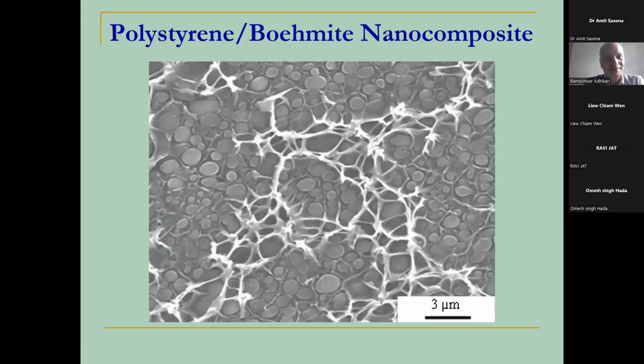Another example, this is the polystyrene with boehmite nanocomposites. These are the particles of boehmite. This here, highly filled polymer it was. And in that case, when the polymer was highly filled, you see the volume occupied by the polymer was very small. When the brittle polymers occupy a very small volume, when they are a very thin layer, they have the ability to flow like tough plastics, like flexible plastics, like polyethylene or polypropylene. And this is why they produce these kind of fibrillar structures on the fracture surface.